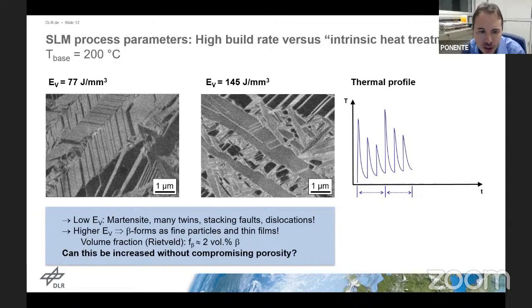And in fact, XRD shows that there is already 2% of beta phase formed in this material. It's a BCC phase, whereas the martensite, the alpha prime, or the alpha phase in the titanium system is an HCP phase. So increasing the volume energy density increases the amount of beta phase. It starts to decompose the martensite and stabilize the microstructure, which I will come back to with the heat treatments in a moment. So first thing we asked in this case, for instance, can this